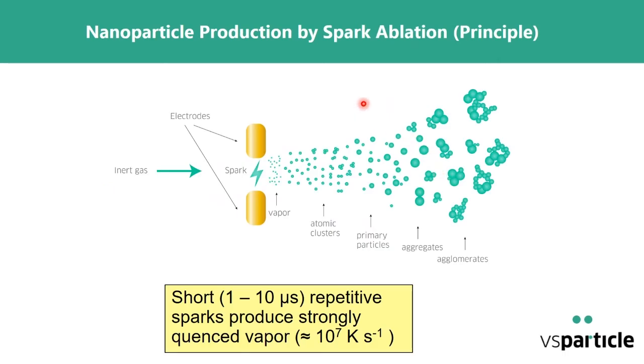And this is a little bit more in detail what it looks like. You have these two electrodes, and there are repetitive sparks between these electrodes, and every spark emits a cloud of vapor. And this cloud of vapor condenses to form first atomic clusters, and then what we call the primary particles, that grow up to a size of about 5 nanometers, and they stay nice and round because they coalesce. The melting point is much, much lower of these particles than the bulk, and that's why they stay nice and round. But when they grow still bigger, they tend to form such agglomerated structures.